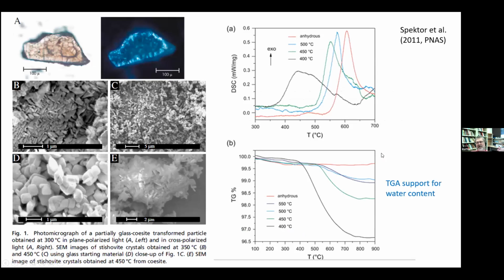And here's the TGA support. This is another nice thing about a multi-anvil. I mean, since then, there's been some great diamond cell work on the hydrostishovite at the beamlines, but this is actually the best way to get water content, thermogravimetric analysis, which was done at Davis in Navrotsky's lab by Emil Stoyanov. And you can see this is anhydrous stishovite, and then you can see the percents get up to, in these samples at 9 GPa, 3 weight percent or more water. So this is a very thirsty stishovite.